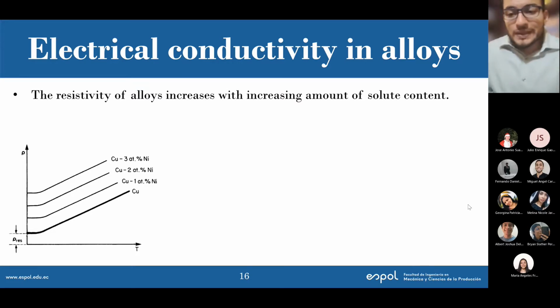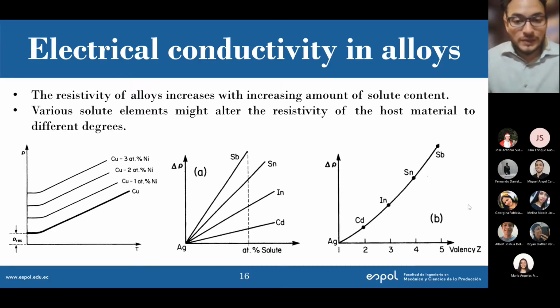That makes sense, right? You have a variation in the lattice parameter. Just by adding other material, the lattice parameter will change. There might be scattering processes, or I will probably have more incoherent scattering processes. There will also be local charge induced, because if I put, let's say, cadmium versus indium, I have a local charge of 2 versus a local charge of 3, so it changes, right? And even just having silver with cadmium, I have a local charge that is obviously influencing a higher probability for scattering, right? And obviously having incoherent scattering. So it makes sense.